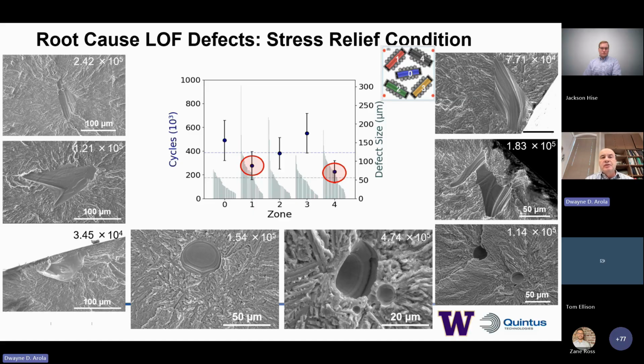This is now in a stress relief condition. So here you're looking at cycles to failure, and you're looking at those individual zones. And I point out these 2 zones, 1 and 4, near the back of the machine that are exhibiting comparatively low fatigue life, significantly lower than you see with regards to the zones 0 and then 2 and 3. So important to recognize for a machine, but not necessarily very desirable, because what you want is not to have that spatial specificity in terms of performance.